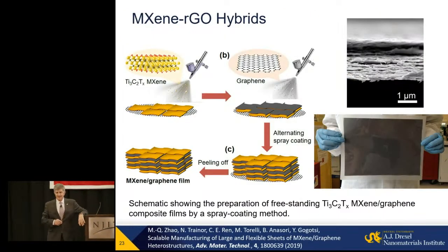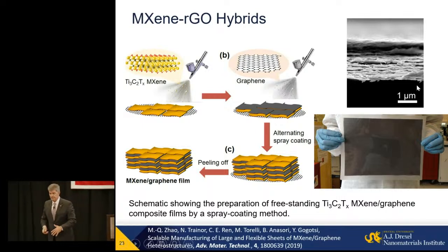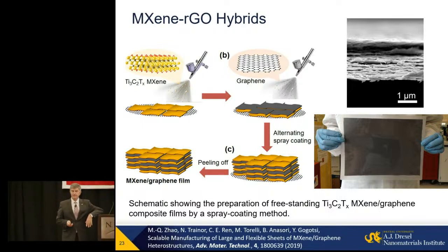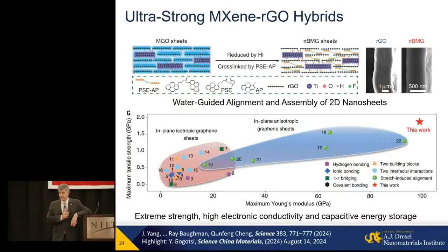Well, Mark was a pioneer in combining graphene with MXene. And you remember what I mentioned at the beginning. We have many, many two-dimensional building blocks, and they allow us to achieve combinations of properties that can be made in a very simple way again. He did it by spray coating layer by layer and making this large sheet of material. You see in a cross-section it looks similar to graphene paper, and he studied electrochemical properties. We were looking for electrode materials here.